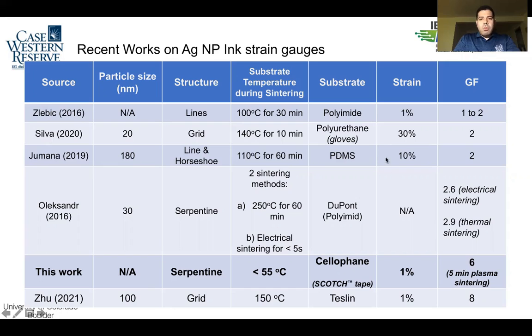The common substrates used were polyamide, polyurethane, PDMS, polyimide, and Teslin. But if you look at the substrate temperature, you will see all of them use medium to high temperature, at least 100 degrees Celsius, for 10 minutes to 1 hour. And that is called the curing time, which varies depending on the structure and the particle size. While for our work, our substrate temperature during sintering was much less than 100 degrees Celsius. It was 55 degrees Celsius, and we printed our silver ink on cellophane.